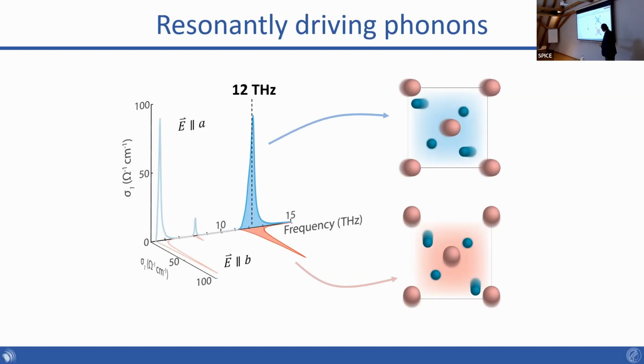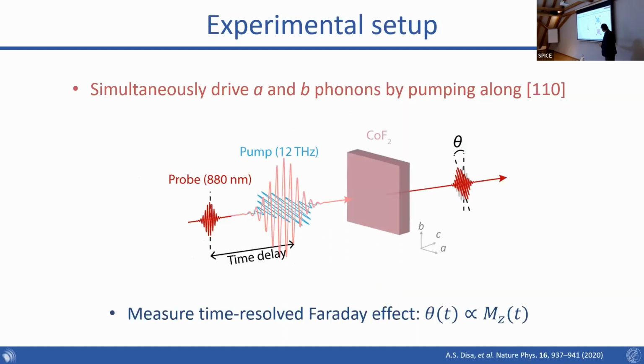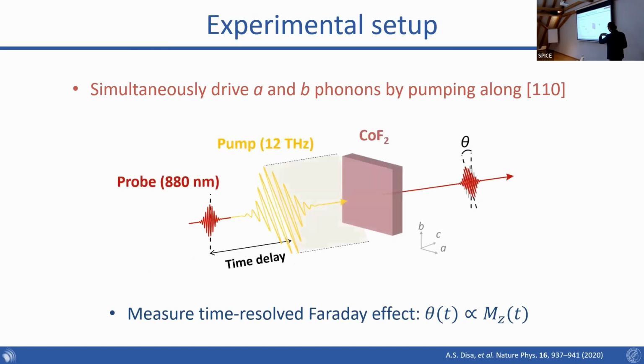Okay, so essentially now we just carry out a simple pump-probe experiment where we pump these two modes with two resonant terahertz pulses, and we probe using the Faraday effect to track the magnetization dynamics. In practice, two orthogonal infrared active modes, or two orthogonal terahertz pulses, is essentially the same as a linear pulse that can be oriented along some direction. So we actually use in practice a single terahertz pulse, which is oriented along the 110 axis to excite both of those modes simultaneously. And so this is the experiment that we carry out.